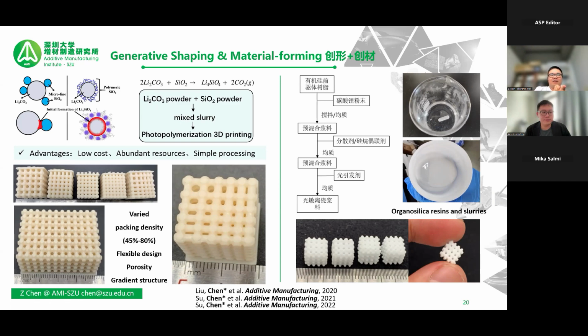are firstly cost effective, low cost economically, and secondly, they are no longer sensitive to air. Because they are cheap and not sensitive to air, we can mix them together into a mixed slurry, then do the 3D printing. The 3D printing in this process makes the shape, so there is a generation of the shape. Secondly, at high temperature, these two materials react together. It's like reaction sintering. Then we have a generation of new material, which is the target material, lithium orthosilicate. So low cost, abundant resources, and simple processing. This will overcome the two issues I previously reported.